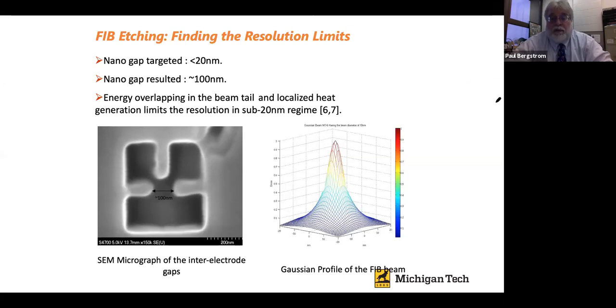And so because of the profile of the ion beam, this is a model of the profile of the ion beam, there's enough energy that is transmitted to the substrate that it's very difficult to get structures under 100 nanometers just by straight up ion beam etching.